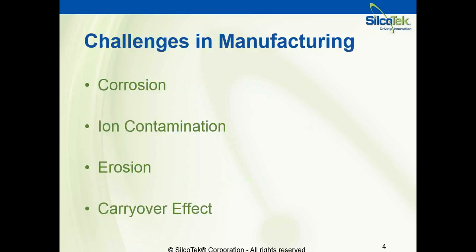So amongst the many challenges in manufacturing that are driven by these demands of the industry, there are four primary problems that our coatings will solve. And those are corrosion, ion contamination, specifically from various metals, erosion within the chamber, which leads to particulate and more ion contamination, and carryover effect and absorption within the chamber, which could bring problems from the following cycles of the process.